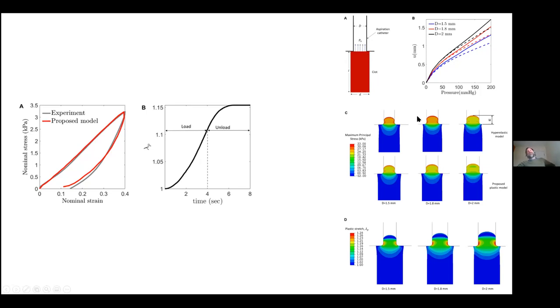And also there's evidence emerging that if you do a cyclic pressure, you get a better result for aspiration. And we've checked that this is not the result of viscoelasticity, and it's not the result of friction. We've checked these things. So the last remaining option is that it's possibly a result of permanent plastic deformation that gradually emerges during a dynamic aspiration. So that's an example of how we apply these complicated plasticity models to soft tissue, and in particular to blood clots.